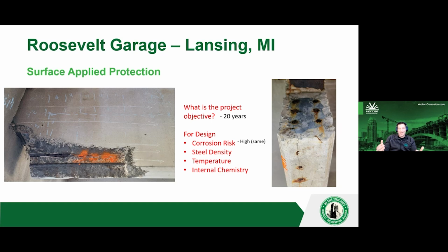Corrosion risk, high. It's roughly the same as the other examples, sorry. Steel density, it's actually much lower than the other ones. You can see there's only like 6 strands. You take those into account. And then there's a couple of stirrups and vertical bars here. But overall, steel density was lower. Temperature, same-ish as the other ones. The internal chemistry, it's the same. Vector Galvashield alkaline.